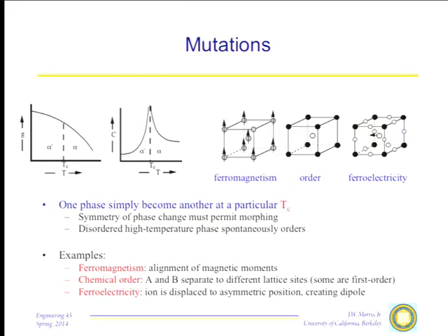From a crystallographic point of view, there is a dramatic difference, a symmetry difference, between a situation in which these vectors are randomly aligned and a situation in which there is statistical preference for them to align in one direction, no matter how small. The minute I establish a preferential direction for those magnetic moments, I have a ferromagnetic material. But the transition from a paramagnetic material to a ferromagnetic material does not have to be dramatic. In fact, it isn't. What happens is we have randomly aligned moments. When we hit the Curie point, there becomes just a statistical tendency for them to become aligned, which gives me a unique axis.